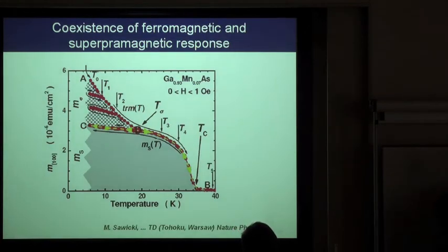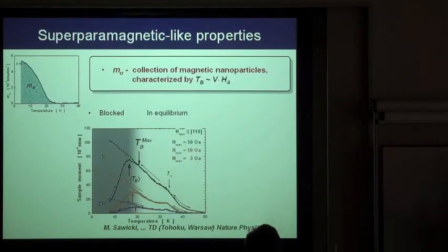And I mentioned that we have this superparamagnetic, ferromagnetic grain superimposed. And do we have experimental evidence for that? Yes. If you do very careful measurements of samples close to the metal-insulator transition, you will see that you have a reversible contribution from the ferromagnetic phase, but also you have irreversibility at low temperatures. Irreversibility means that the actual magnetization depends on the conditions under which you start to cool down, with or without magnetic field; you get a different curve.